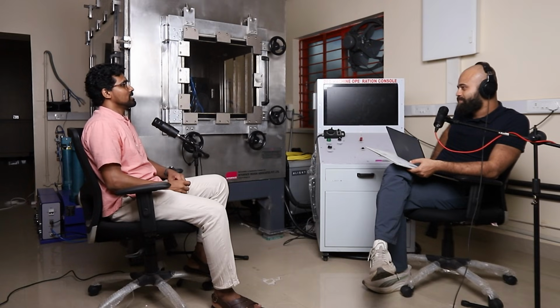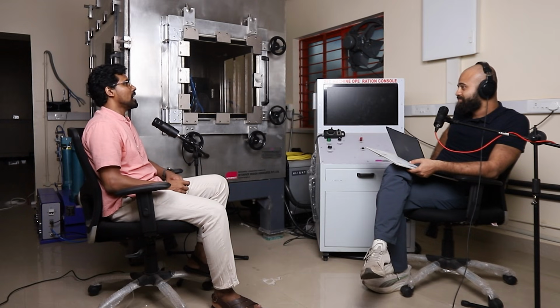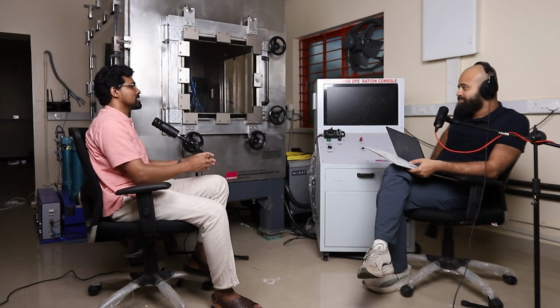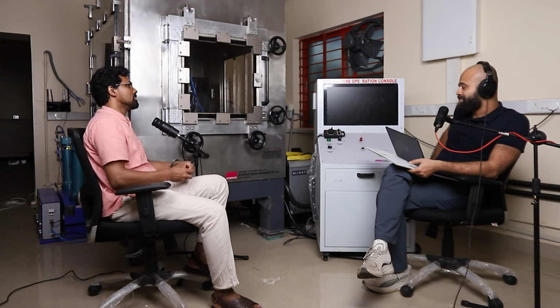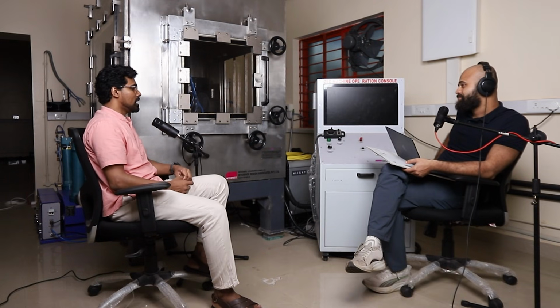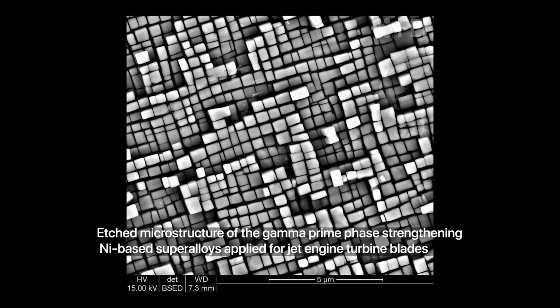So they came up with this alloy which has a lower nucleation density, but also has something on a microstructural scale which we won't go into, but I'll just mention it: it has a gamma prime precipitate microstructure which leads to much superior properties. Because of those, this particular alloy was invented, and then they started manufacturing the blades as single crystal.